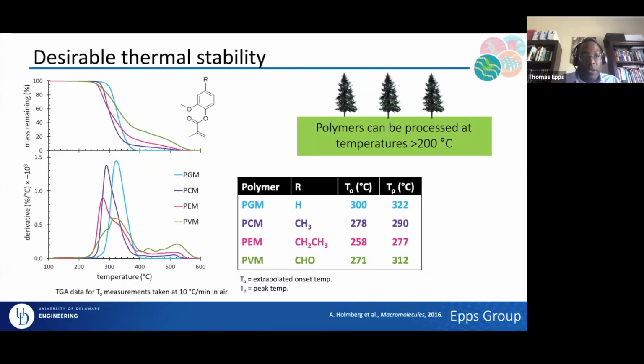Now we can take these materials and also look at thermal stability. So we can do thermogravimetric analysis. I will mention that in our case, we do it in air as opposed to nitrogen. One of the reasons that we do this in air is because it more closely mimics what might be done in a commercial process. So in this particular case, the key point is just showing some curves here, but the key point is that the onsets of degradation, as you can see, are all between about 250 and 300 degrees Celsius. So basically what that means is that even for the worst performing material here, which is the ethyl version of the methacrylate, we basically have about 150 degree glass transition to degradation temperature window for these materials.